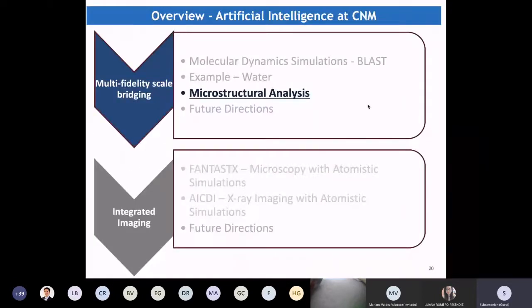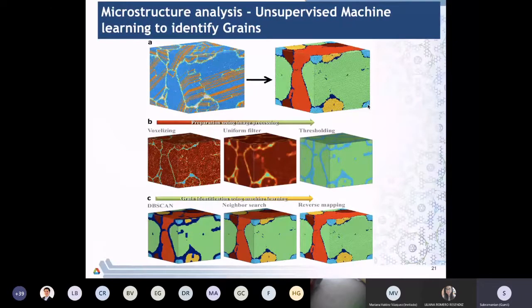We want to also go ahead and perform microstructure analysis for these large-scale simulations that we are doing. One of the things we found when we were carrying out these large-scale MD simulations of grain growth is that there was no algorithm available which would allow us to classify these grains in full 3D. To address that, we came up with an algorithm for grain boundary classification that takes advantage of some image processing and unsupervised machine learning, such as a clustering algorithm, to identify these domains which are grains. You do these filterings to remove the stacking faults or any other defects, and then you do a clustering to identify the grain boundaries.